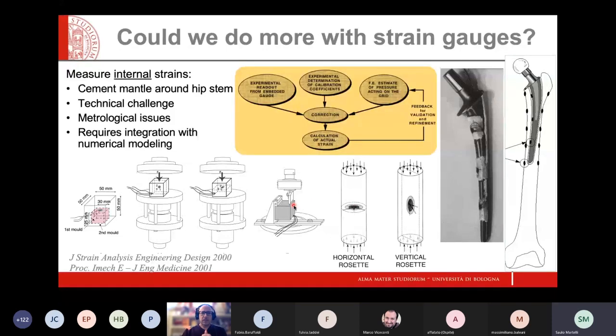Sadly, we found out that we had quite some artifacts when the strain gauge was incorporated in the bone cement, so we realized it was a problem. Then we realized it was a big problem, and then we thought this was a great opportunity to, again, combine the experimental measurements, the calibration coefficients, and FE models to provide the information to correct the readout. So we built a loop where the experiments were validating the FE model, and the FE model was improving the experimental measurements.